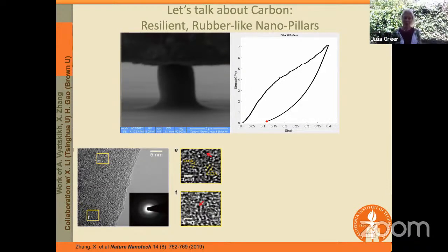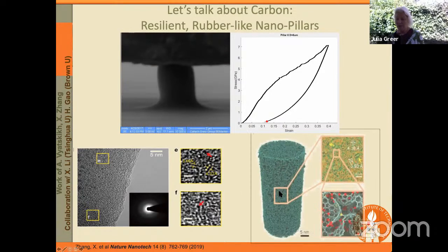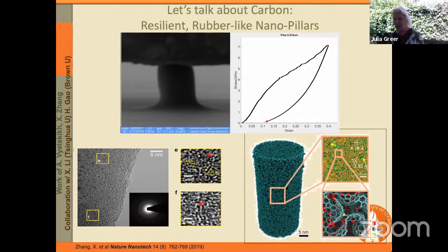And so what we discovered is when you look very carefully at the microstructure of this glassy carbon, you see these curved strands. And even though the structure is amorphous or glassy, we discovered that there are small regions of graphene-like ribbons. You can see that they're separated by a very small distance of about 3 angstroms. And so these segments of graphene, or effectively sp2 hybridized carbon, is what allows these regions to shear with respect to one another without undergoing global failure. So we collaborated with a group at Tsinghua University who was able to perform molecular dynamic simulations. And what you can see here is the representation of the microstructure that we uncovered experimentally done through atomistic simulations. And you can see that these are the curved regions here of sp2 hybridized carbon.